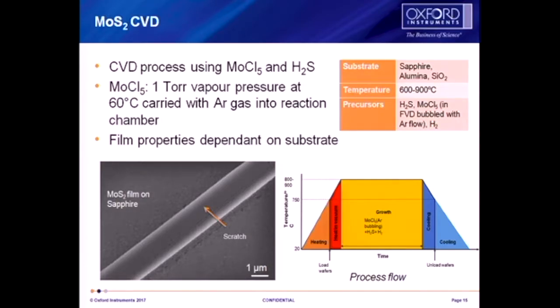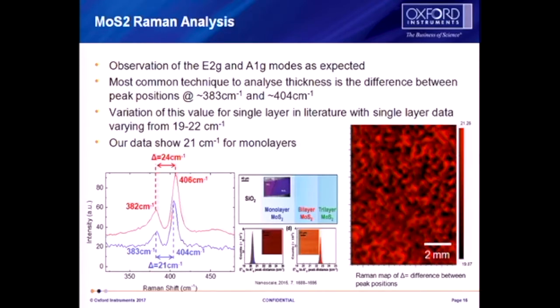For the molybdenum, you actually need the molybdenum chloride or a metal oxide, which you have to heat to sublime and then flow into the system using argon. Again, the best processes we've seen on this, and I will come back to this a bit later from some very recent results that we've put into the slideshow, are between 600 and 900 degrees C, depending on the substrate you're going to deposit on. But by playing with the parameters, you can get very good material.